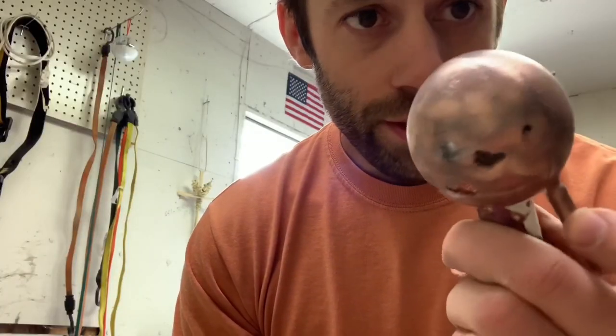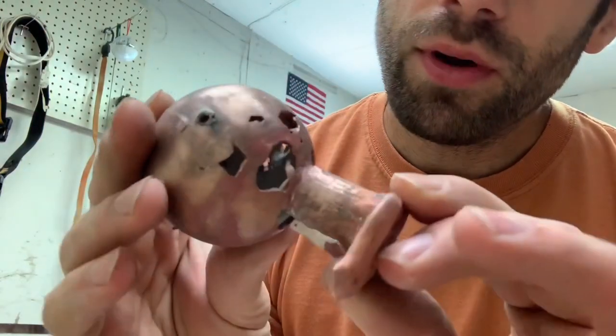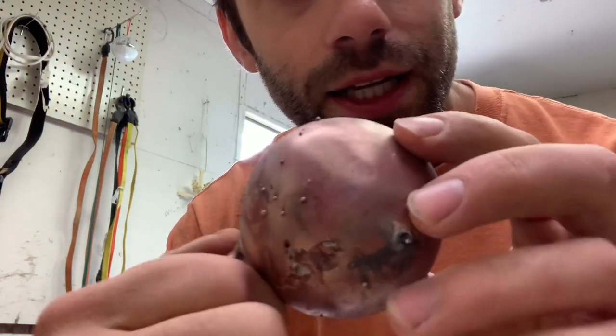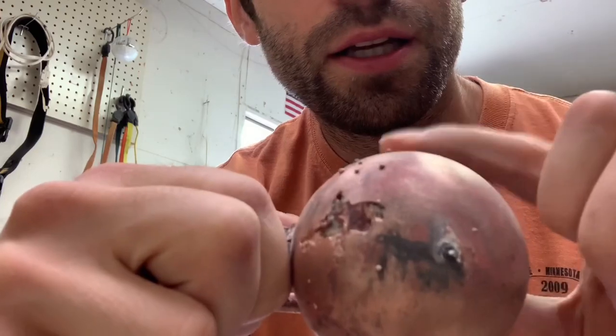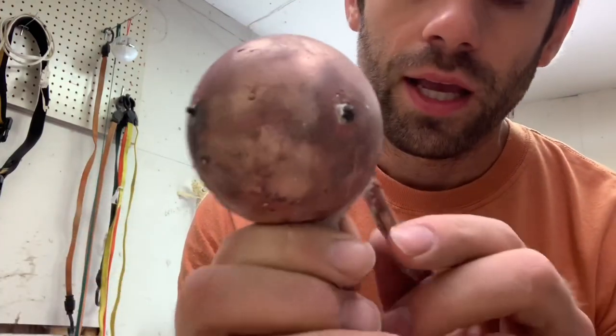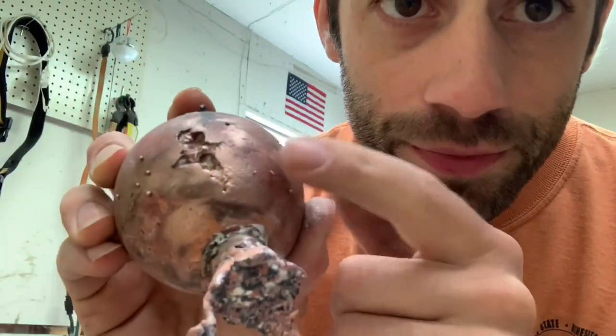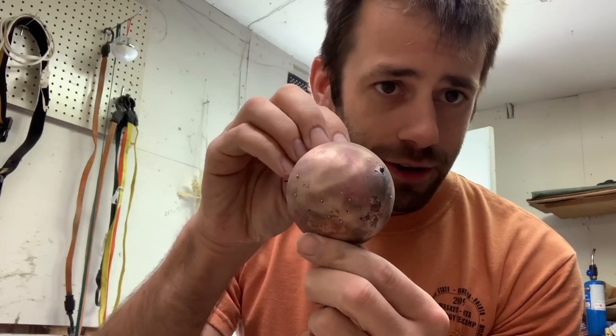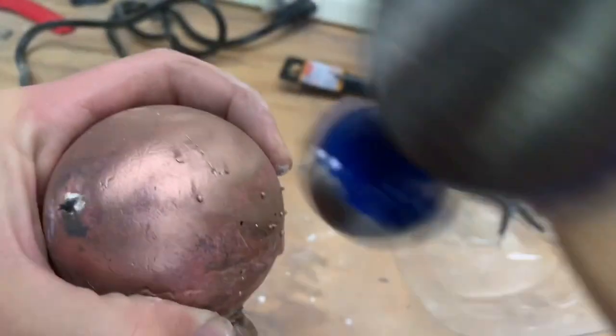The smaller one — the one that didn't bubble — has all these little pockets. It's not what I wanted, but it still looks kind of cool. The bigger one — the one that was bubbling like a volcano — has a lot of little air bubbles. That's because I didn't vacuum cast the investment, but that's okay. It turned out pretty well with just a couple pockets here and there. This is going to be the virus body.